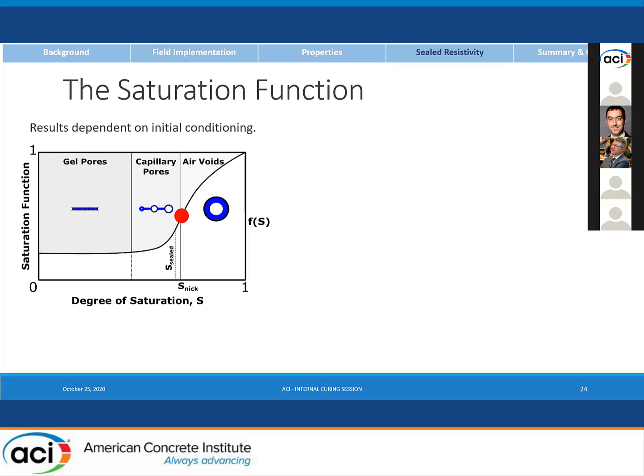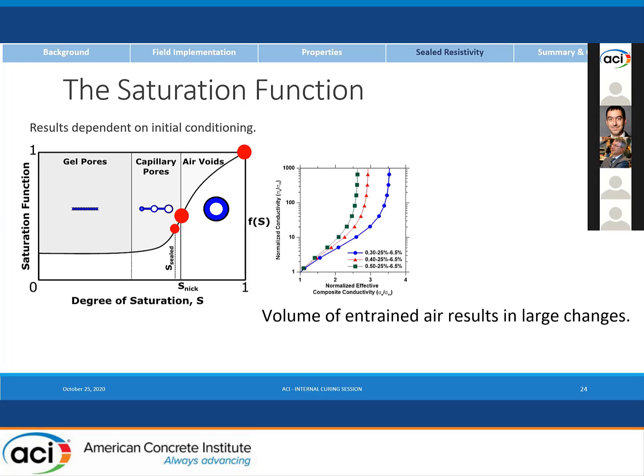So there's points of interest. There's the nick point degree of saturation, which is what the bucket test is getting us most near. And then we have full saturation if we pull a vacuum near 0 torr, where we're filling in the air voids. And then I will just simply note that the sealed degree of saturation is very, very close to the nick point degree of saturation. It turns out that it's about 10% difference on the average from some basic calculations.